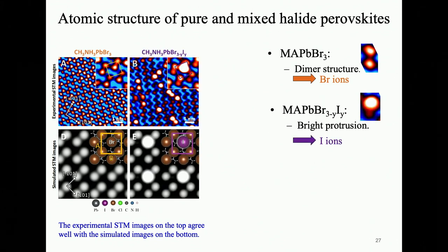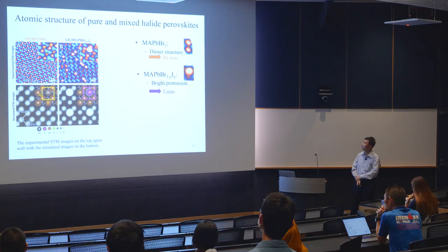Then, by vacuum deposition of a small amount of PbI2, we substituted part of the bromine surface ions with iodine ions. Because iodine ions have a larger ion radius, they appear as bright protrusions in the STM image.